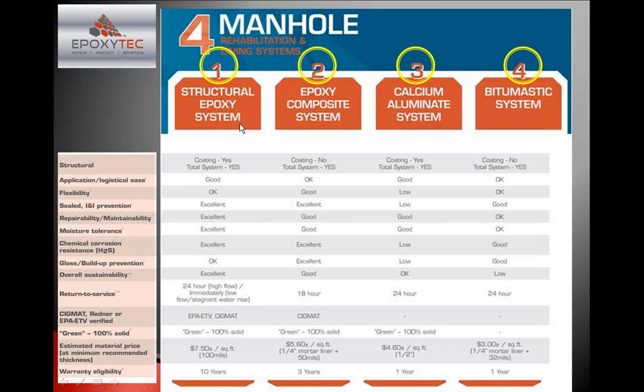So if we take, for example, the city of Hollywood in Florida, I often use this as an example of some of the worst conditions that we've ever found. We have very old infrastructure. A lot of it is still brick. We have water falling out between the bricks. We have water pouring in. We have very high hydrogen sulfide. Every time there's a tidal increase or tidal decrease, anytime the tide comes in or goes out, it increases the hydrostatic pressure on the structures. So we have very high levels of water infiltration, not only rainwater, but groundwater and tidal salt water, but then we also have very high levels of hydrogen sulfide. And we have structural deterioration, and so these need to be rebuilt. So that's where we have the worst kinds of conditions, and that's where we would typically recommend a product like Epoxytec CPP that will give you the biggest bang for your buck on a long-term rehabilitation system. Okay, we can move on.